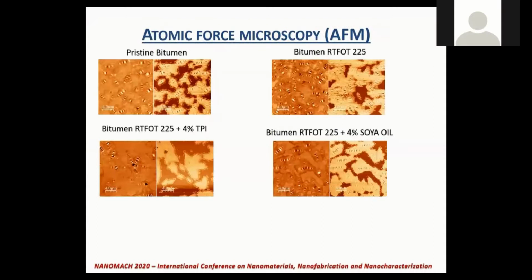In the next slide, we show the phase and the topography images of the pristine and aged bitumen samples with and without 4% additives. In the pristine bitumen and aged bitumen samples, the domain sizes are similar. The interconnection of the domains appears to be greater in the case of the aged bitumen sample than in the pristine bitumen sample. In the soy oil and the TPI samples, the domains are much larger, and in the case of the TPI, they seem to be less connected than in the soy oil case.